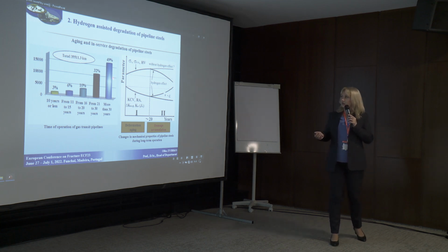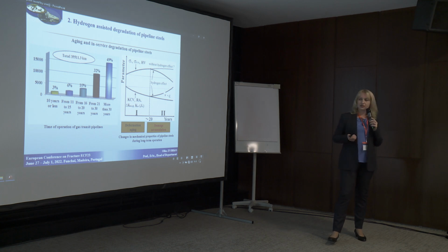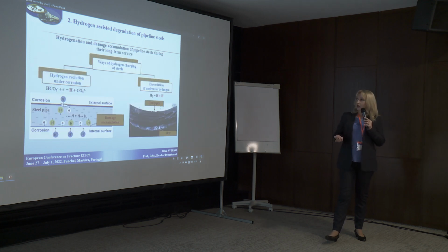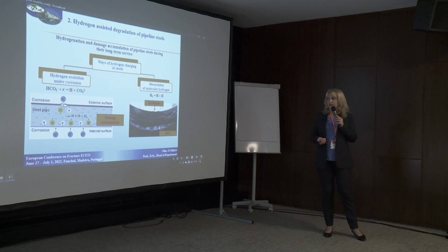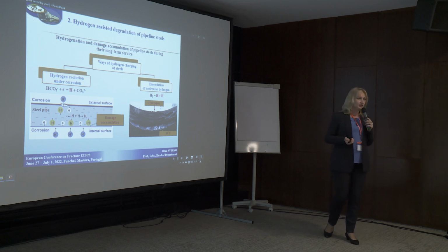Here we can see that two main stages of in-service degradation of pipeline steels were distinguished. The first stage is deformation aging, and the second one is damage accumulation. And an important role in the second one is played by hydrogen charging of pipeline steels under operation. And as you know, the main problems of in-service degradation are embrittlement and also deterioration of mechanical and corrosion properties. So here you can see how hydrogen is involved in damaging and degradation of pipeline steels under operation.